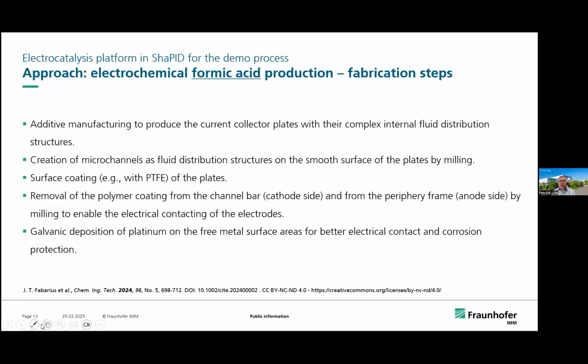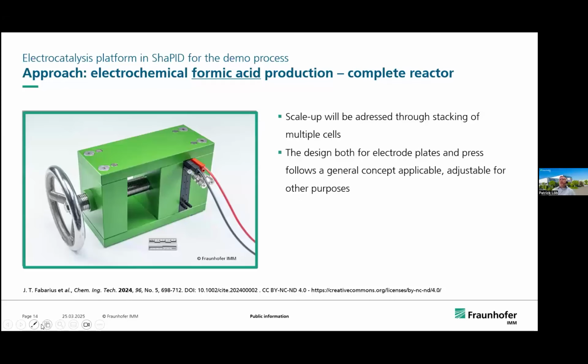We have some surface coating with Teflon on the plates. In some parts, we have to remove the polymer coating again, from the periphery, to have an electric contact of the electrodes. And in some parts we even made galvanic deposition of platinum on the free metal surfaces for better electric contact and corrosion protection. This is a point I want to outline, that we spent quite a lot of engineering effort in this reactor type. And here's the electrochemical reactor we used in our lab scale investigations.